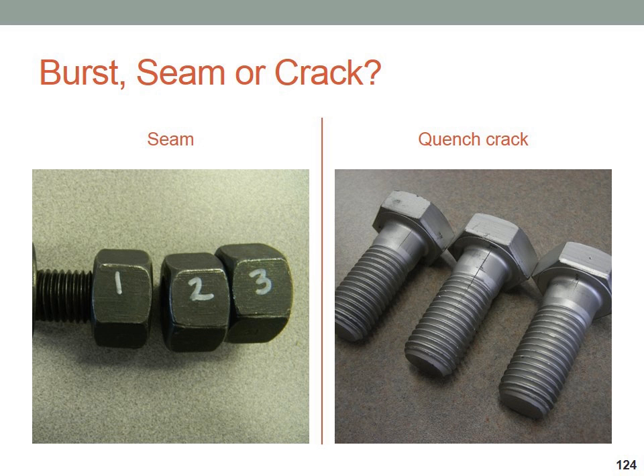Now, you don't want to discount some sort of a seam. In this case, there are seams from the raw material processing on a nut. And in this case, what you might think is a seam on a structural bolt is in fact a quench crack. Seams are not that bad. Quench cracks can be horrible. Quench cracks are not super common, but they do happen. I have a feeling a lot of them end up in structures and are not caught.